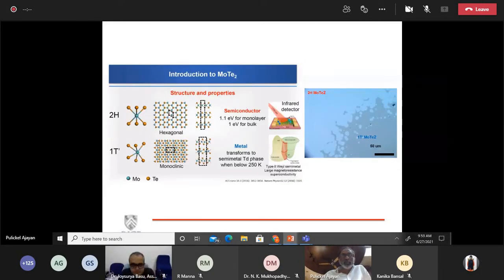There is another potential of building these lateral heterostructures, and that is with the different phases that I mentioned. So in the case of BN graphene, there were different compositions, and electronically they were quite different. In these type of materials like molybdenum telluride, you can have this 2H and 1T prime phase, where the electronic properties are different, but the composition is the same. So if I try to grow molybdenum telluride, typically, what you end up with is these 2H phase and the 1T prime phase that are merged together within a single unit thickness. And 2H is semiconducting and 1T prime is a metallic phase. They're slightly different in structure, but they're pretty close in terms of lattice parameter and so on.